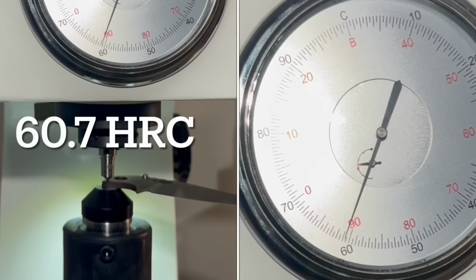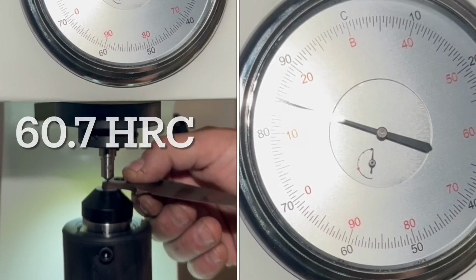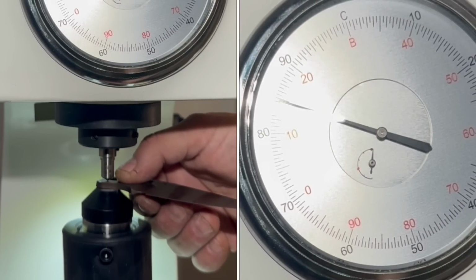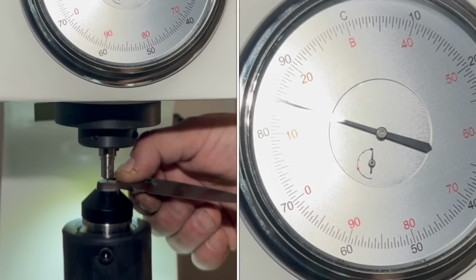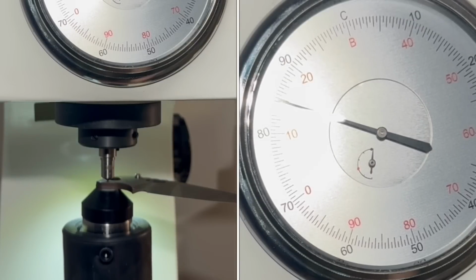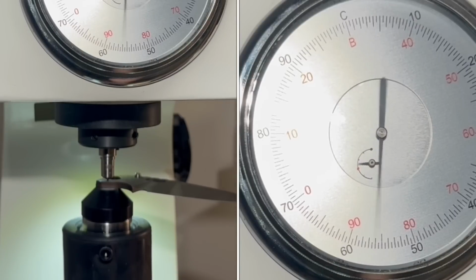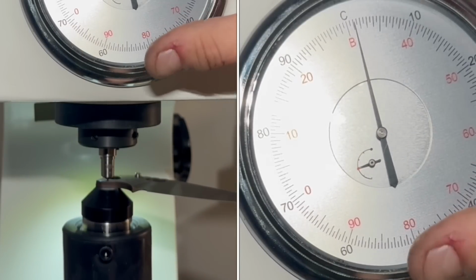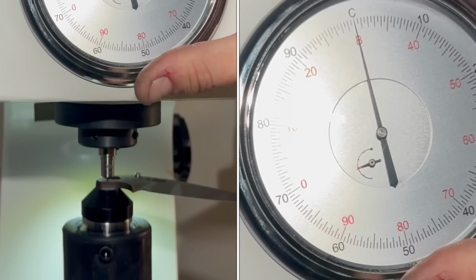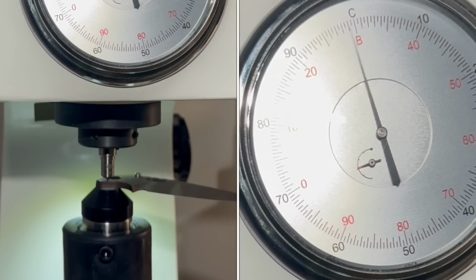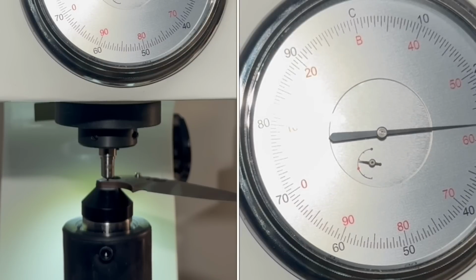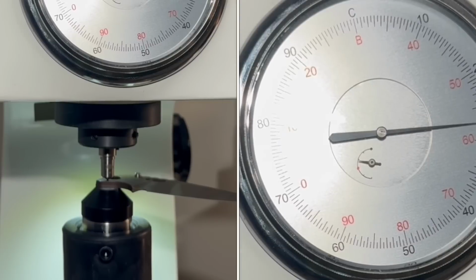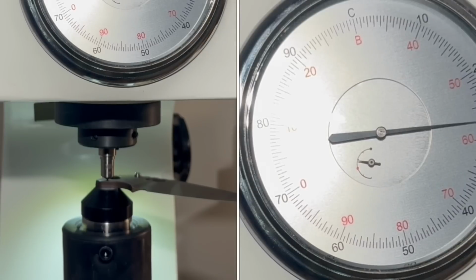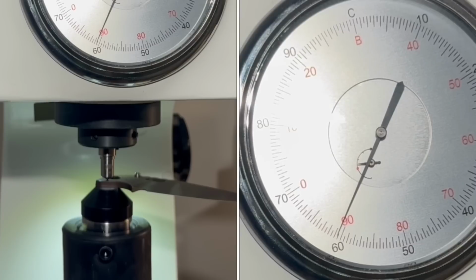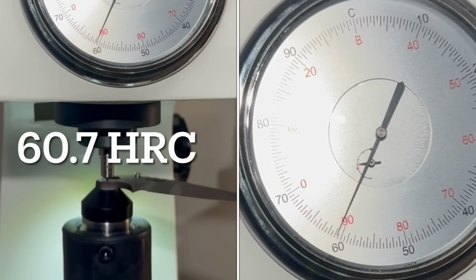All right, what we got here is 60.7 on the first poke. Let's do 2 more pokes. All such measuring equipment has built-in error, and the standard for Rockwell testers allows plus or minus 1 point accuracy and plus or minus half a point HRC repeatability. So technically you can get plus or minus 1.5 point error, which seldom happens because these devices are calibrated, and when they're calibrated properly, you expect a much smaller error. That said, the second poke comes in at 60.7 HRC again.